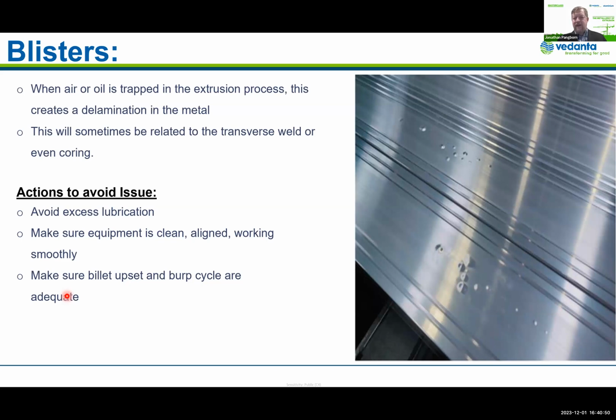It's a very loose fit to the container, which is why we run a burp cycle, upset the billet, and then release the pressurized air, and why we pay attention to the sheared surface and so forth. It certainly can sometimes be related to transverse weld, possibly coring, but that's less likely. Split billets can be an issue for blisters, particularly if you have, for example, a log shear and you have a high level of deformation on the front and back surfaces. This will definitely be more of an issue for sheared metal.